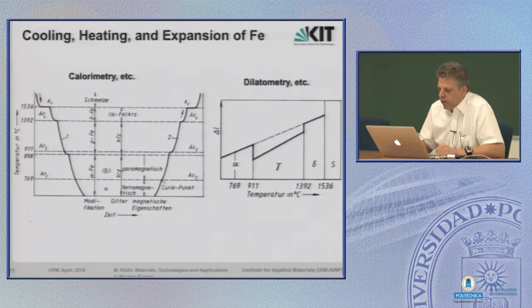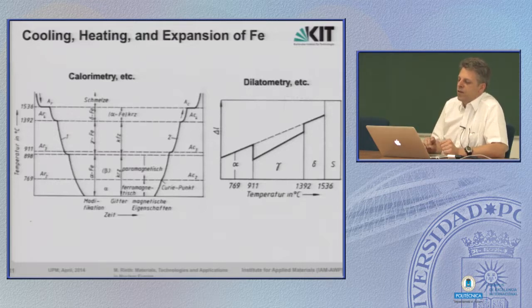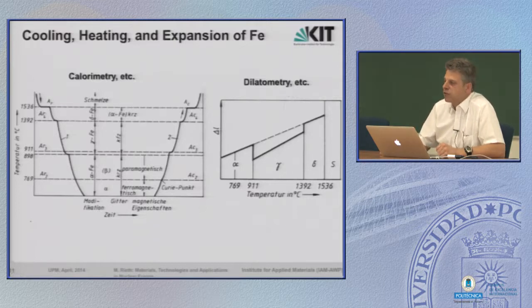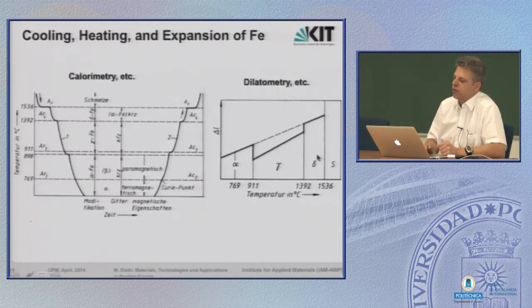You all know for iron that we have phase transitions due to the lattice structure depending on temperature. At the lower temperature range, it's a BCC structured iron. Then with higher temperature, the lattice changes in its configuration into FCC structure, and only at very high temperature again back to BCC structure. The lower temperature BCC structure is called alpha iron, gamma iron, that's the part where we have FCC structure, delta iron, that's again where we have BCC structure, but on the higher temperatures.